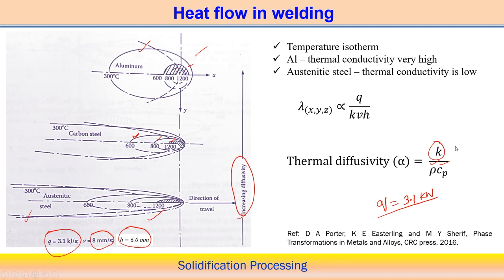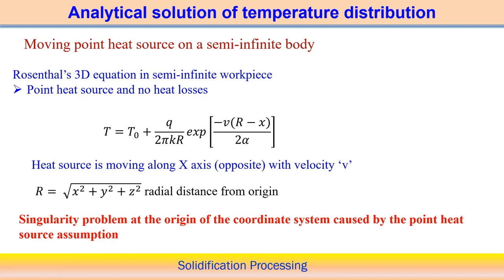So once we understand the temperature distribution, and of course through the analysis of the heat flow in the welding process, we can utilize it in different ways. Now I will try to explain the analytical solution of the temperature distribution for another kind of solution. It is the most widely available solution associated with any kind of fusion welding process, called the moving point heat source on a semi infinite body. Moving point heat source means the heat source from the arc; although in practice it is a distributed heat source, we assume a point heat source, because then we can get a very simple analytical solution of the temperature distribution.